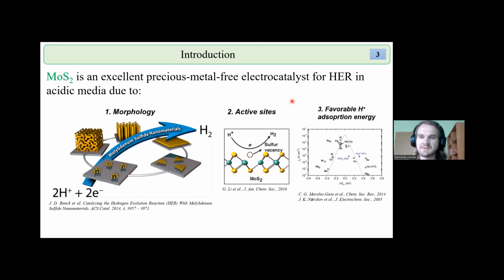but it can be used for other heterogeneous electrocatalysis processes. And again, the reason it is useful in water splitting is because, as shown in this volcano plot, which plots the free Gibbs hydrogen adsorption energy against the exchange current density of the catalyst, molybdenum sulfide is near the top of the plot. These are specifically edge sites, but other sites can have different energies. The mechanism is similar to that of platinum, and it is highly efficient.